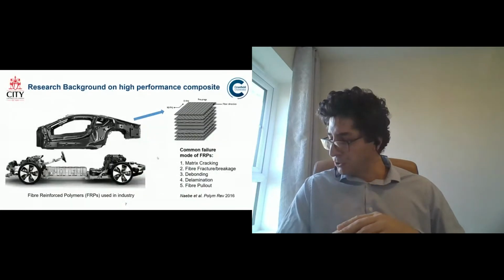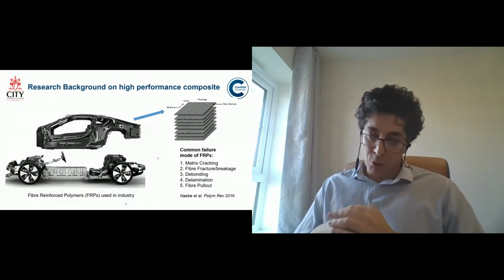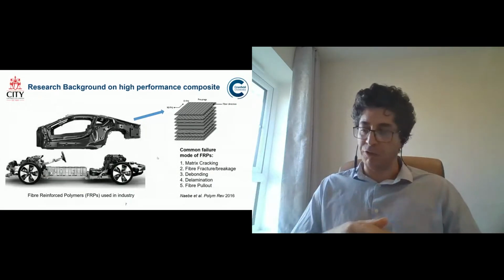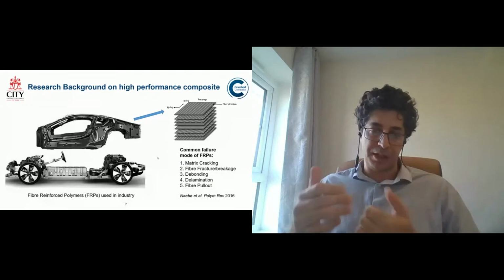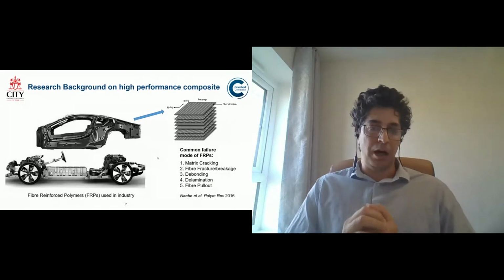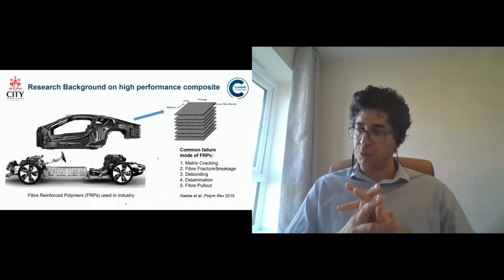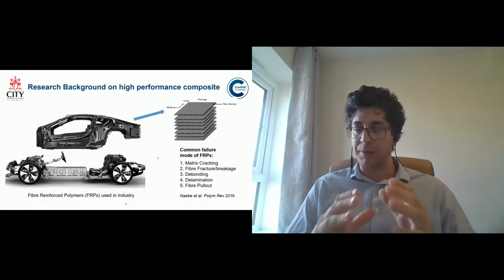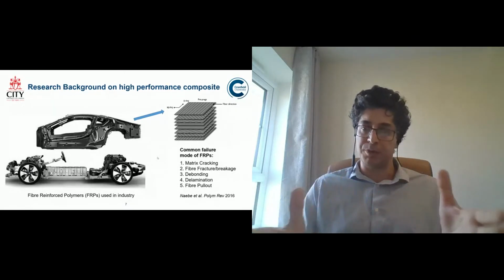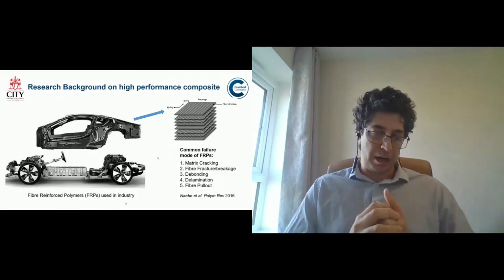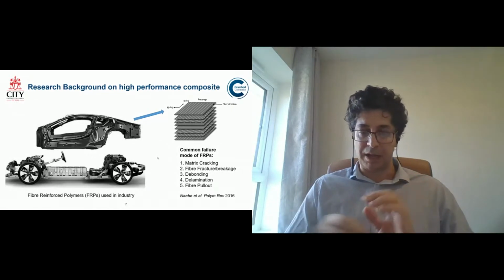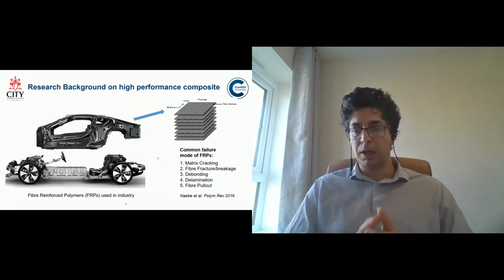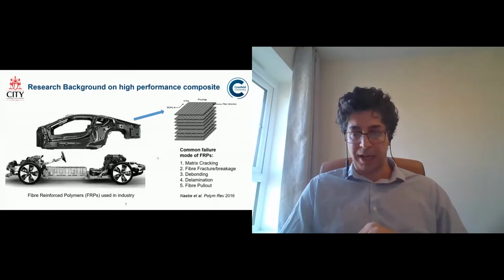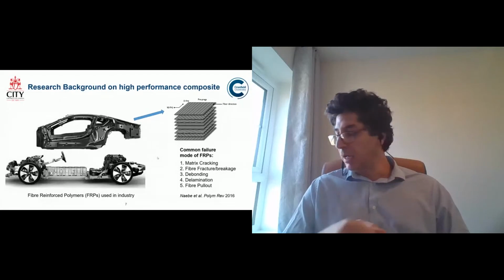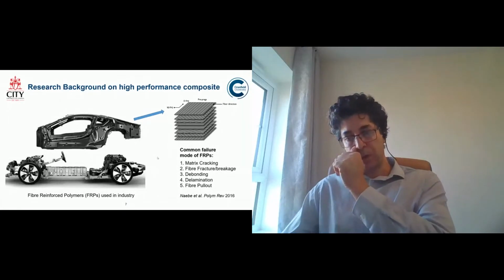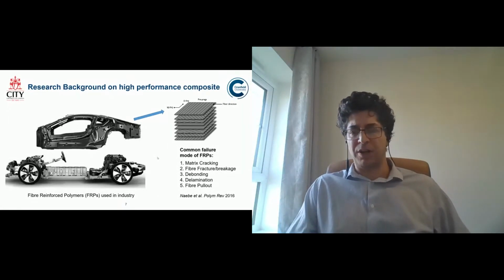And if you look at the composite structures, made of multi-millions of structures itself, because we've got multi-layers of composite layup all around. I intentionally put this because we wanted to say that it's not only in aerospace, it can be in any high-performance structure like automotive, that you may end up with composite damage across matrix cracking, a polymer matrix. We're talking about fiber fracture breakage, disbonding or debonding, delamination, and fiber pullout. So loads of research being done there.